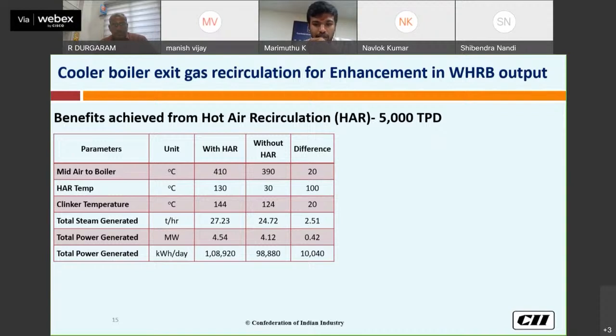These are the benefits achieved from hot air recirculation for the unit of 5,000 TPD. In this figure, we can see that without hot air circulation, the mid-air to the boiler is around 390. With hot air circulation, it increases by around 20 degrees. Hot air temperature, instead of ambient 30, we have given around 130 degrees centigrade. Increasing the air temperature also increases the clinker temperature by around 20 degrees. The steam generation in the existing case was 24.7, and with hot air circulation we achieved 27.23, so around 2.5 tons increase. Power generation has also increased by around 0.42 megawatt.